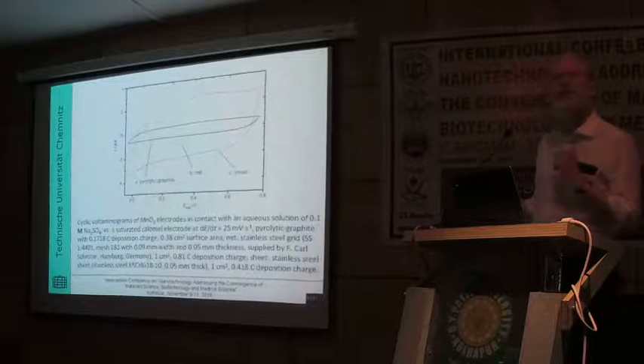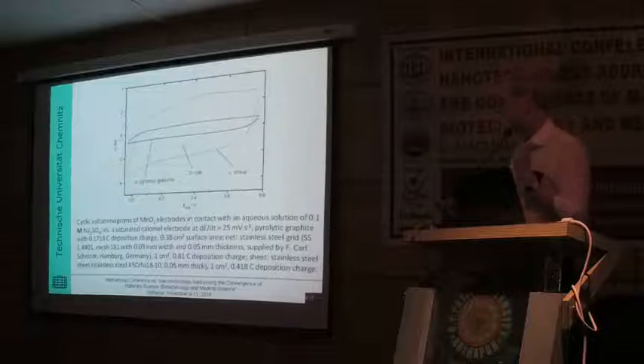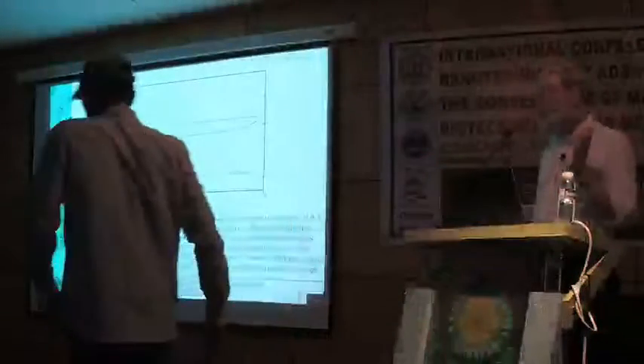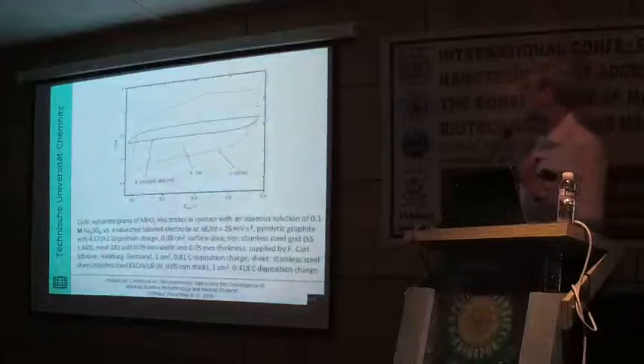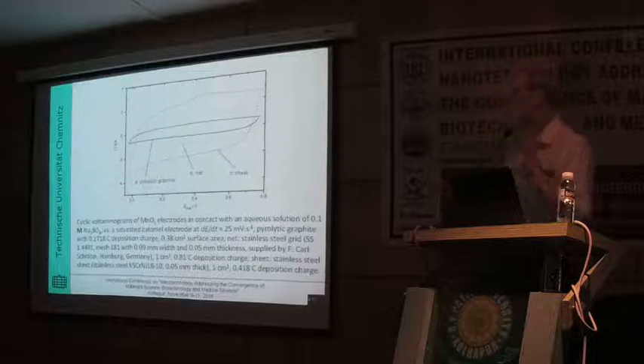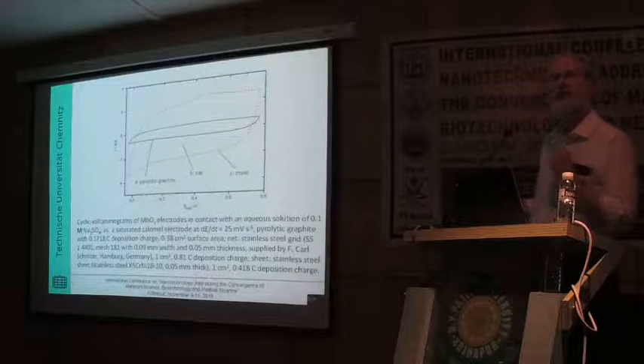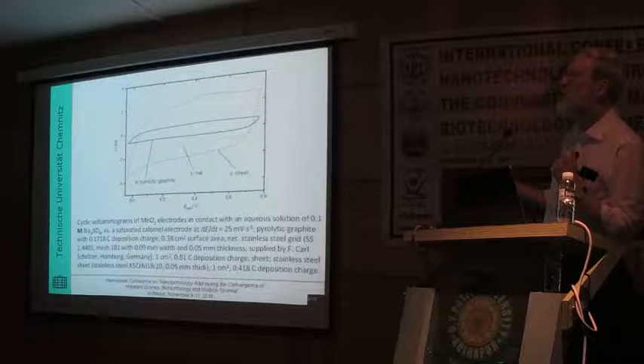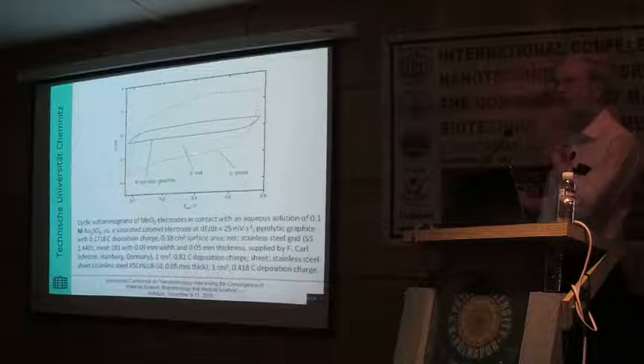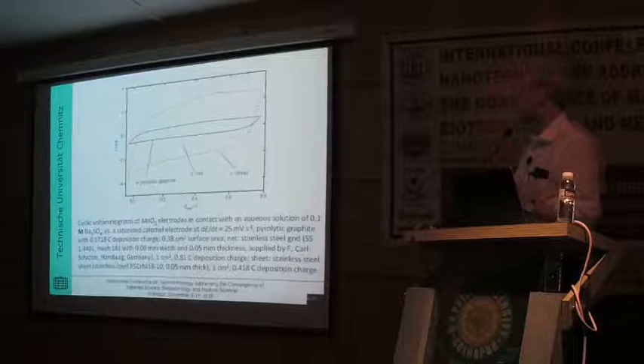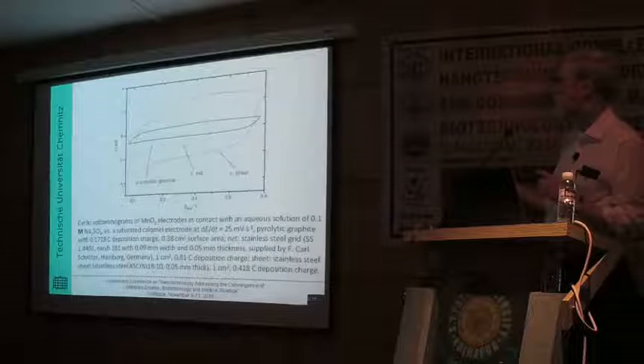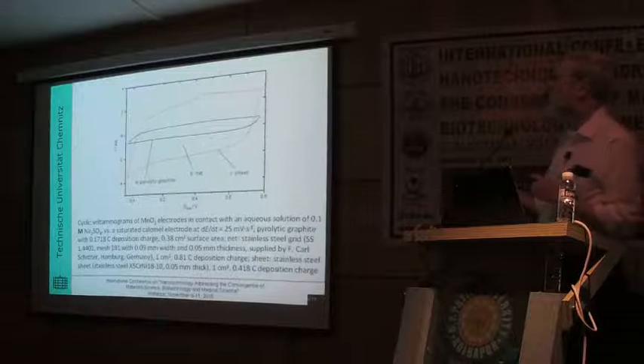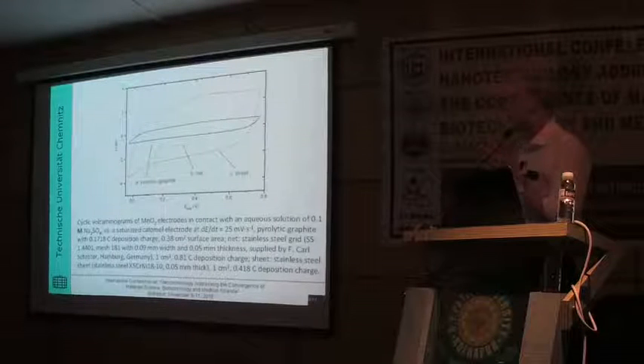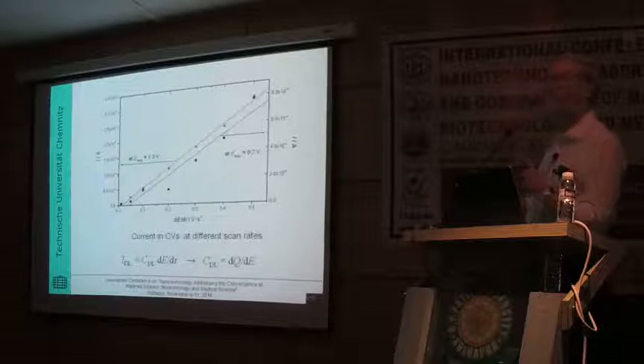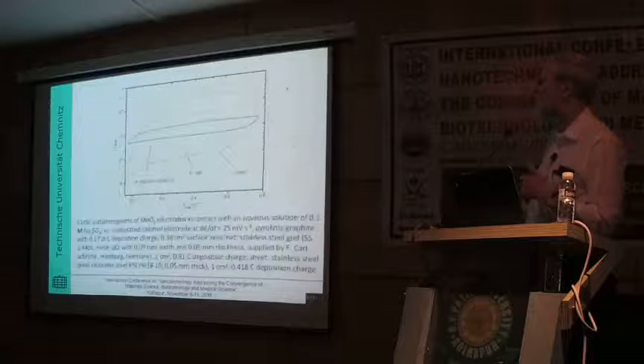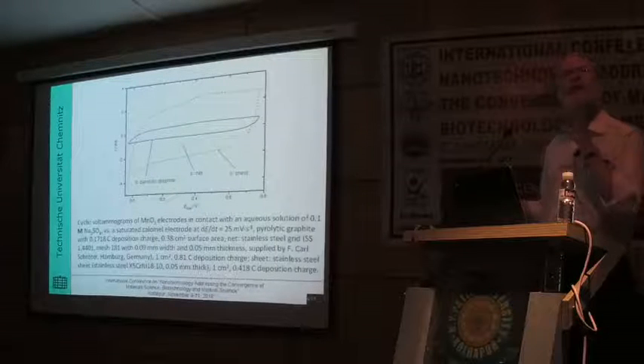Now we move to some more realistic material, which, for example, is manganese dioxide. Manganese dioxide, much cheaper, environmentally acceptable, and so on. And in this example, just for an illustration, we have coated manganese dioxide on a piece of graphite. It's a very smooth surface. We have coated the manganese dioxide on a stainless steel sheet. The use of stainless steel in sheets and in nets was introduced into our group by Deepak Dubal when he was a Humboldt Fellow in our group a few years ago. And we have coated the manganese dioxide onto a stainless steel net. Once again, I could make such a plot, and the response is not rectangular, but it is very close to a rectangle.